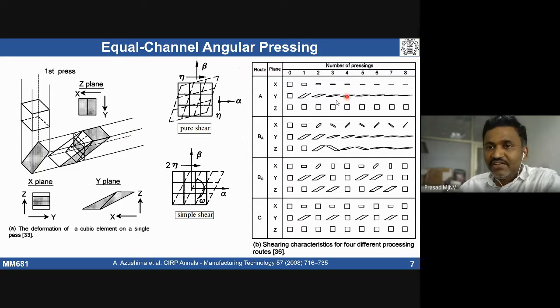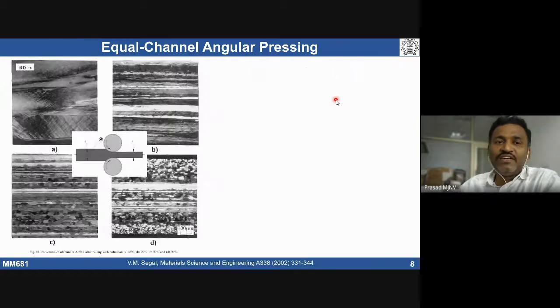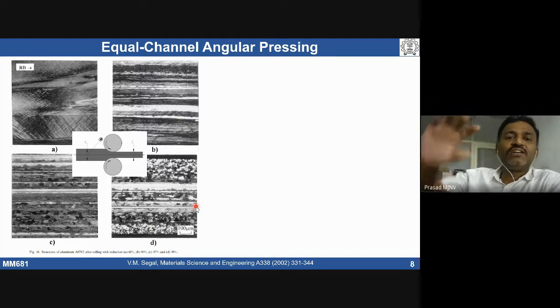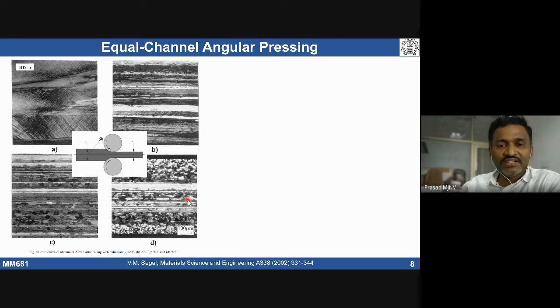We are giving a cross loading. We are creating some vortex metal flow. The metal flow is basically changing every time. If I take a simple rolling operation, and you deform aluminum material 68%, 90%, 97%, 99%, typically we get elongated grains. We may see some subgrain structure, but if you deform in one direction uniaxially under rolling, we get elongated grains.